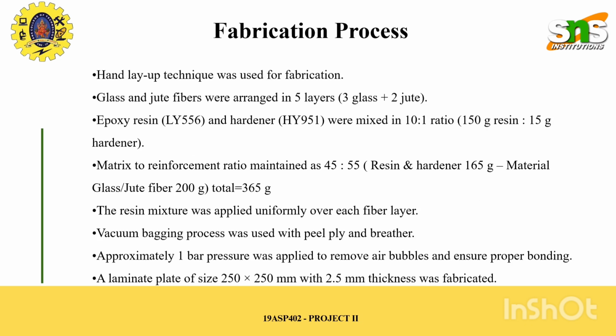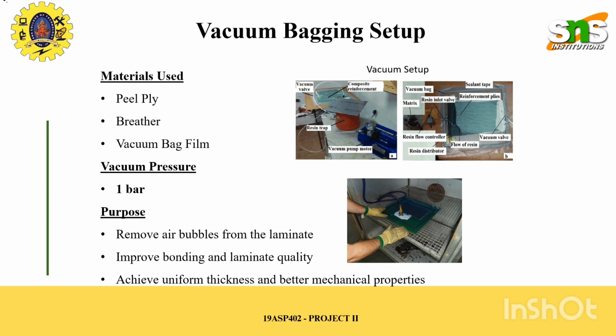The fabrication of the composite is carried out using the hand layup technique. Glass and jute fibers are arranged in 5 layers, consisting of 3 layers of glass fiber and 2 layers of jute fiber. The epoxy resin and hardener mixture is applied evenly over each layer. A matrix-to-reinforcement ratio of 45:55 is maintained. Vacuum bagging is then used to remove air bubbles and improve bonding between layers.